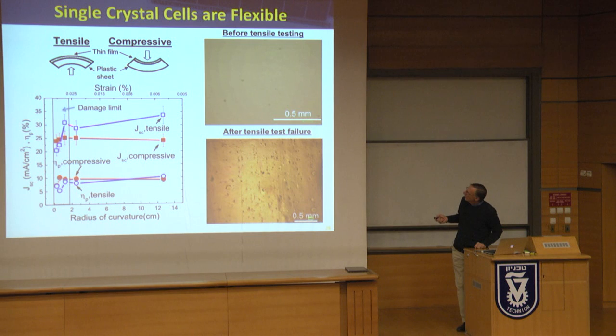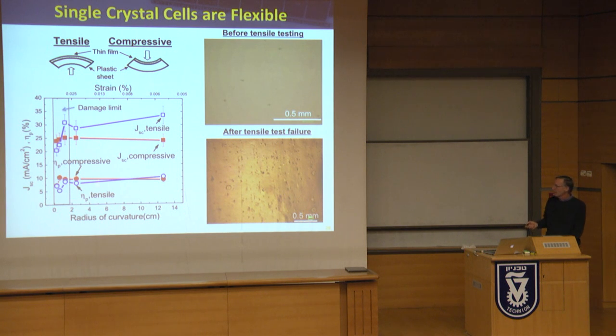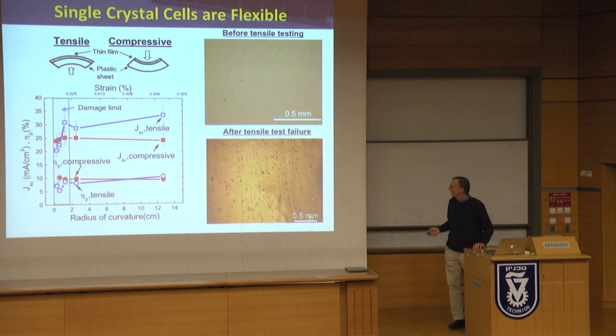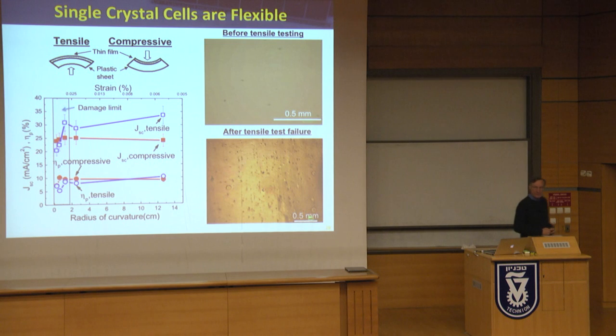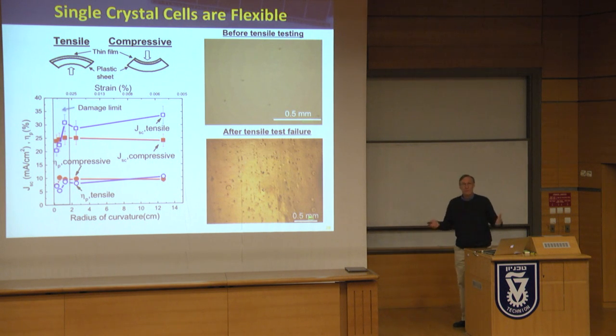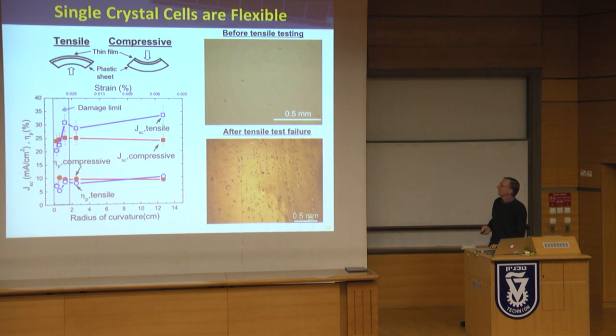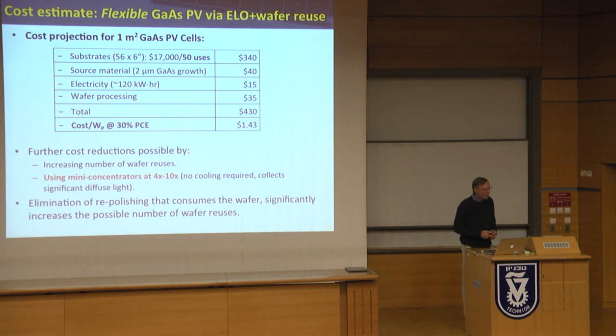And this is where we're curling these wafers over, or these, we got the plastic, we have the epi on top of it. And surprisingly, we can get these right down to about a centimeter radius of curvature without damage to the wafer. At some point, you start to get dislocations forming like crazy. So this is very lightweight. You can deploy it in rolls, and you get 24% out of it. It's not too bad. So this is the economics.